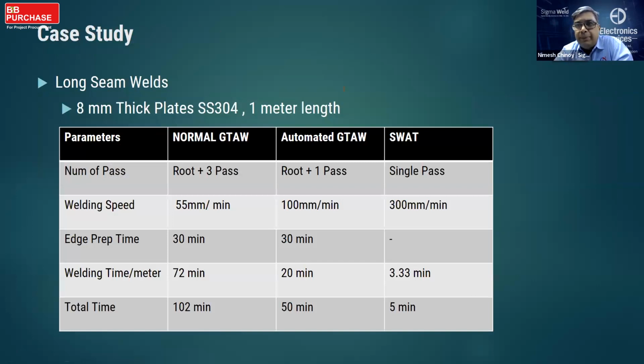If you were to do a long seam by normal manual TIG welding process, about 8 mm thick SS, it would take you close to about 102 minutes, considering 30 minutes for edge preparation, manual welding speed of 55 millimeters a minute, and root plus 3-4 passes to weld, about 72 minutes of weld time. Same thing if you were to do an automated process with an auto TIG, you would get root plus one pass. You could do it in two passes at 100 millimeters a minute. Edge preparation of 30 minutes. Welding time 20 minutes. Total project time 50 minutes.